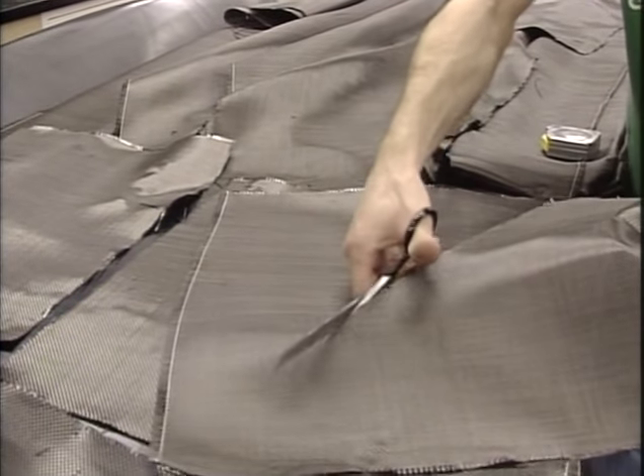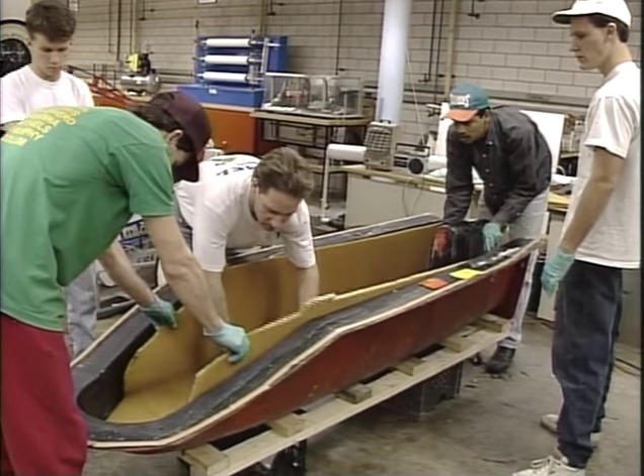The top shell will be constructed in a single piece requiring only one template. However, the bottom shell would need to cover the wheel housing and would require three pieces. A separate template was made for the wheel housing, and a full-scale template was also made to cut the Nomex honeycomb. The honeycomb template was cut two inches shy of any outer dimensions of the part. This would effectively seal the honeycomb and give the part better resistance to interlaminar peel and shear forces, while also allowing the inner skin to form a strong mechanical bond to the outer carbon fiber skin.